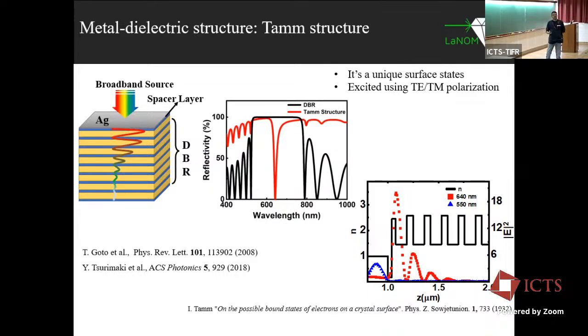How do you make sure this is a cavity mode? We do field calculations, and looking at the intensity as a function of spatial distance, you can see that at the surface the field is getting localized. Around 18 times localization is there. We engineered it at 640 nanometer, and if you send 550 nanometer light, the light gets reflected back.